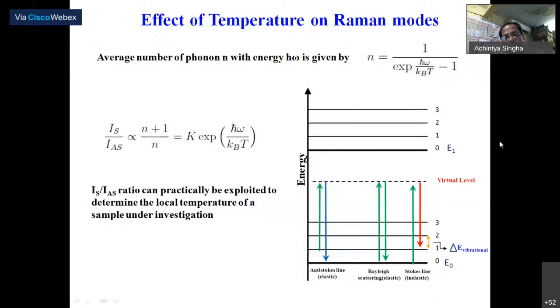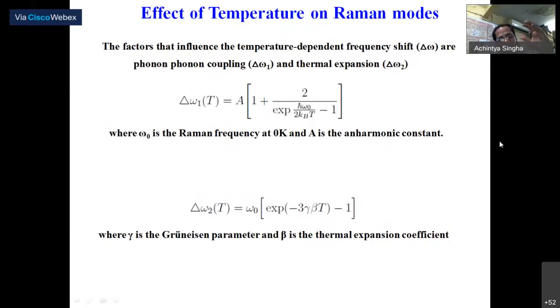Now go next. Okay, this is from the intensity change, and also the energy. When you increase the temperature, there will be some phonon interaction. One phonon will interact with another and create some lower energy phonon, so that will give some energy shift. Similarly, if you increase the temperature, there will be some thermal expansion, which will also increase the lattice constant. So the effect of phonon interaction and thermal expansion together will give you some change of energy. That means the Raman frequency, the phonon frequency of the system, will change.